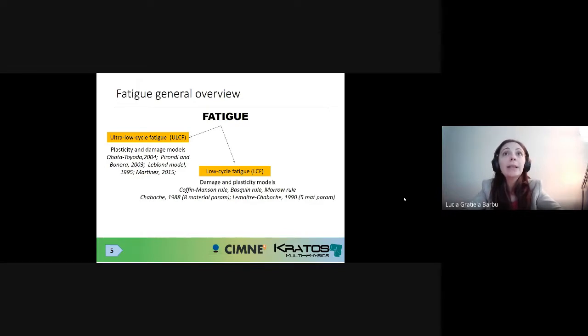Now, low cycle fatigue is somewhat more standard, or more taken into account by the industry, because we have some standard rules which are implemented in different fatigue software. For instance, the Coffin-Manson rule, which is, I believe, the most widely used, the Basquin rule, the Morrow rules. Here is an area where normally you find damage and plasticity models, sometimes joined together. And most of the models developed in this area are based on two base models, I would say, which are the Chaboche model and the Lemaitre-Chaboche model, developed in 1988 and 1990. Now, there are a lot of researchers working in this area, but a lot of the models proposed nowadays are generally extensions, based on these two models.